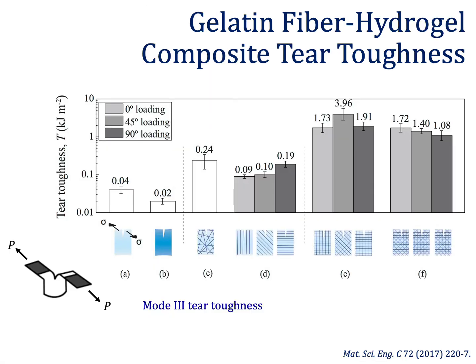When we measure the fracture toughness of these materials, we can get quite a range of behaviors depending on how we orient the fibers within the gel. So if you look on the very left-hand side, we have the toughness of the base material, so the gelatin gels and the alginate gels, and it's very low. Then as we add the randomly oriented fibers, we get an increase in the toughness by about an order of magnitude to 0.2. Then as we orient the fibers a little bit better and make sure that we have fibers present in different orientations, we can see further increases in the toughness of these composites that we've made in the lab.